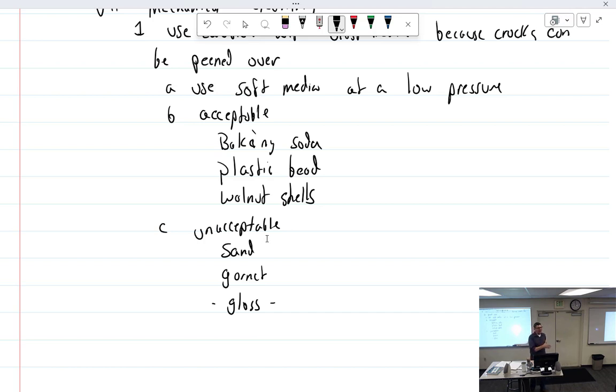At one point, glass was really kind of common, everybody was doing it, but I did notice on my own, before they said don't do it, the glass was peening over some cracks. So I would say, oh no, we obviously have a crack, but you peen it over, and then I couldn't get an indication out of it, but you could see the crack. It just wasn't deep enough to hold the penetrant. And so that became kind of a bad thing. And then as time progressed, service bulletins came out, and said, no, stop using glass. It just creates more problems.